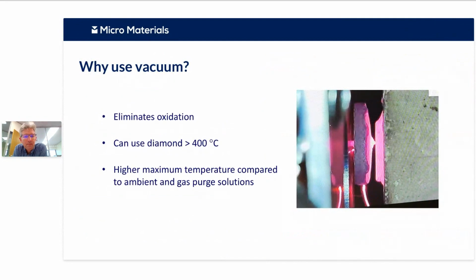So why are we using vacuum in the first place? Well, it's to eliminate oxidation on the tip and the sample side. So diamond itself will graphitize in air above about 400, 450. It's relatively slow if you're not heating the tip, as you don't necessarily need to heat the tip for impact experiments, then as you can see with Hannah's talk there, you can go to a little bit higher temperatures and still use diamond.